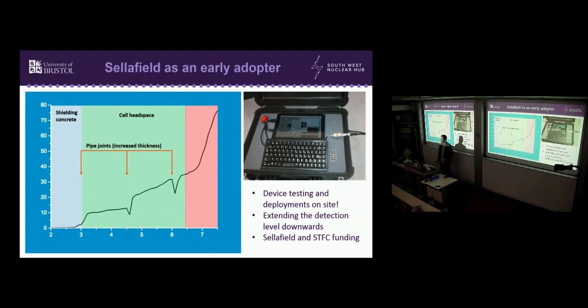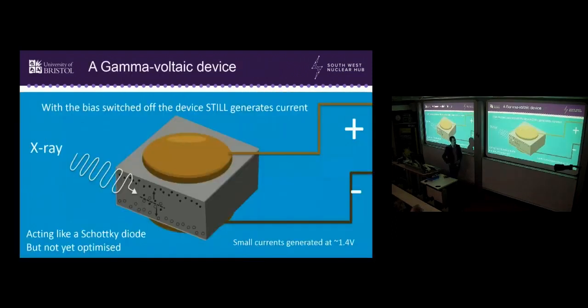So we pat ourselves on the back for developing a new type of technology which works from a low dose of about 0.05 grays per hour up to 24,000 grays per hour. And 24,000 is an incredibly high and extremely lethal dose. So one day we were playing in the lab with our diamond detector and a very strong americium source, and one of my postdocs forgot to turn the 300-volt bias on. And what we found is it still generated a current. Quite a small current compared to what you'd get for 24,000 grays, but it was noticeably quite high above background, just sitting next to quite a good lab source, but with no bias.